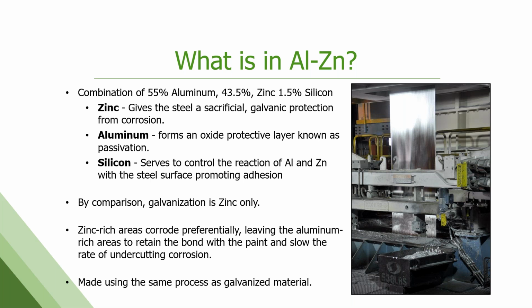It's the same process at the end of the day. It's hot dip galvanized material. The lines look identical. They process almost exactly the same. The difference is the pot mix, right? Instead of being all zinc, you have this aluminum zinc mix. And actually, a lot of steel mills run what we call a dual pot. They'll actually have a pot of both, and they can move the strip between the two. Not uncommon to see that.